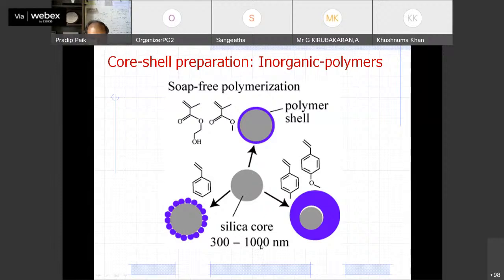Now you see that whenever you change the core diameter, if you would like to make a different one, then you have to take a different core diameter. You can vary it. Silica is a material which is very easy to make in different sizes, let's say from 10 nanometers to 100,000 nanometers, and according to your use you can put it in during the reaction. So the core allows this core shell reaction. Now if you take out the silica, then hollow materials will be there.